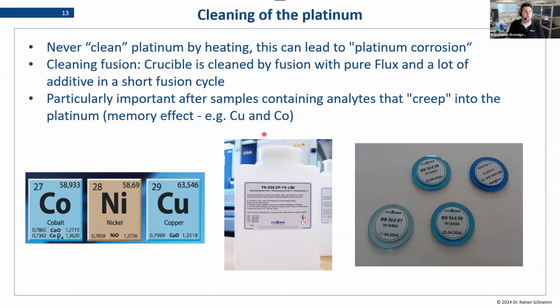There is this known effect from some analytes, copper and cobalt being the most known here. They creep into the platinum ware. There is what they call a memory effect. What that means is if you do one sample and it has copper and cobalt and you do not make a special cleaning afterwards, you will find 500, 300 ppm of that copper or cobalt in your next sample, even though that sample didn't contain any. Because what happens is that these elements go into the dish and then the next sample that doesn't contain them, they get washed out again.